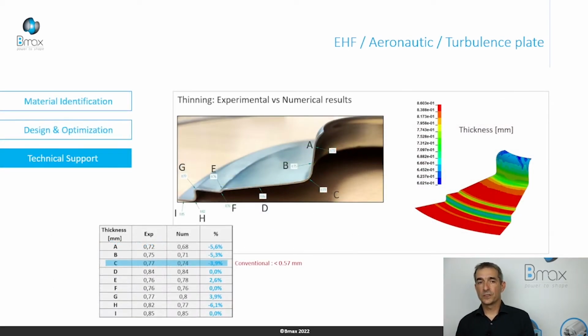When we produce all these parts, we perform a 3D scan to check if we respect the geometrical tolerance. We cut samples to compare the thickness between experience and simulations. The table summarizes all this data. We have a very good compliance between numerical results and experimental ones. All the gaps are less than 6%.